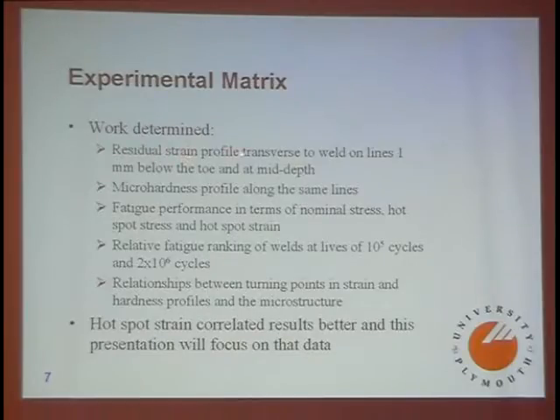So I wanted to measure the residual strain profile transverse to the weld on lines 1mm below the toe and at mid-depth. 1mm below the toe is probably where you've got undercut intrusions and you would expect crack initiation to be occurring, or at least cracks to start growing. So that residual strain and the hardness there might indicate an effect on early crack growth. The mid-depth one I'm sort of assuming dominates the longer crack lengths, and I was interested to see which one might work the best. So I measured residual strain along those lines and micro-hardness profile along the same lines.